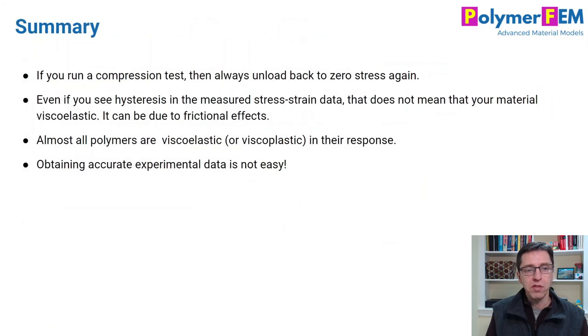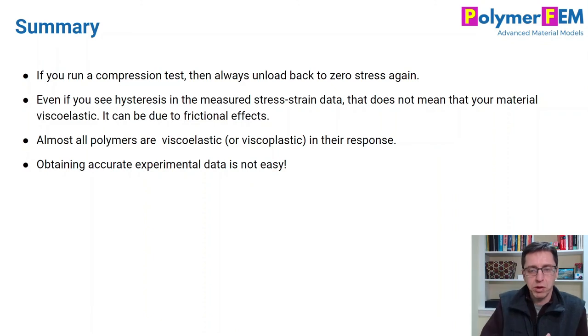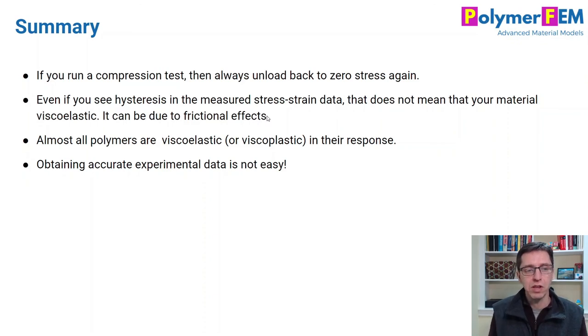To summarize: if you run compression tests, always record the stress during unloading too. You really need to look at the unloading response because it gives you a lot of information — there's no need to stop the test at maximum compressive deformation. Go all the way back. If you see hysteresis or energy dissipation in a single cycle, it does not mean that the material is viscoelastic, as we showed here. It can be due to frictional effects. But if you run your test carefully and reduce the friction effect, then any hysteresis you see is clearly going to be the actual material behavior.